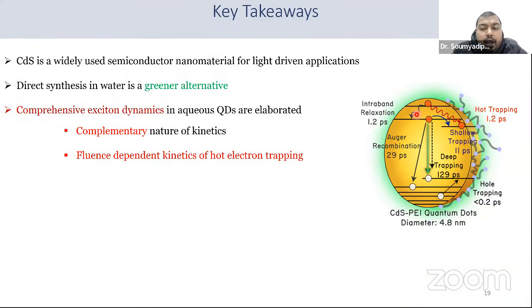So what is happening? What we have is intraband relaxation at around 1.2 picoseconds. We have shallow trapping of 11 picoseconds, deep trapping of 130 picoseconds, and Auger recombination of 29 picoseconds. All these things are going on, and it gives us a good quantum yield. Okay, yeah. So all these things are going on, and this is a kind of well-defined picture of the multi-excitonic relaxation processes in water-soluble CdS quantum dots.